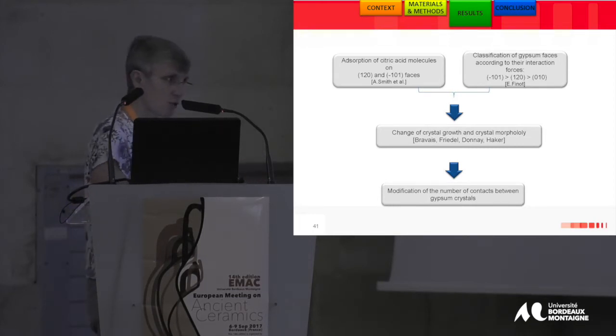Because of this adsorption, it modified the crystal growth, as shown by the Bravais, Friedel, Donnay, Harker theory. Modifying the crystal growth, there is a modification of the morphology, and therefore we modified the number of contacts between the gypsum crystals.